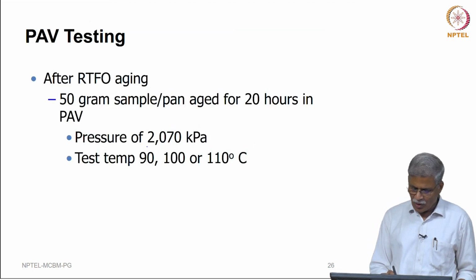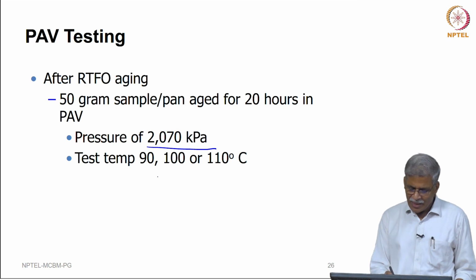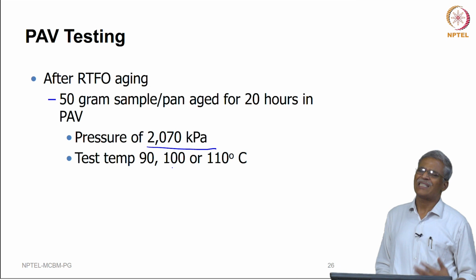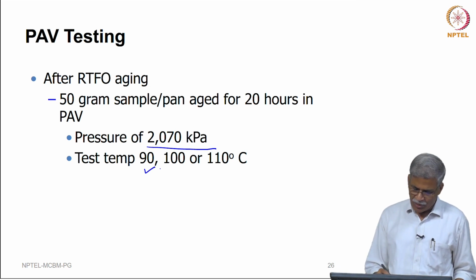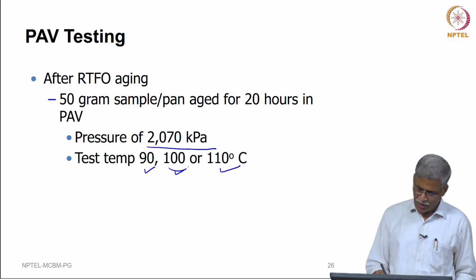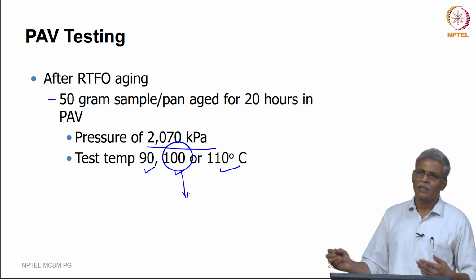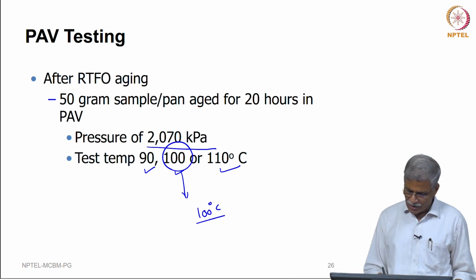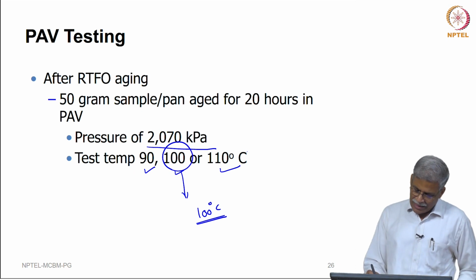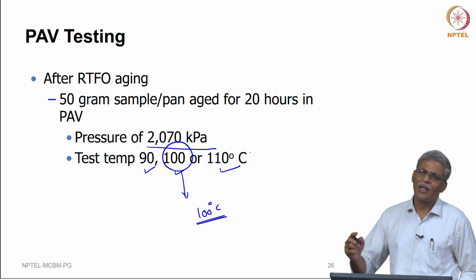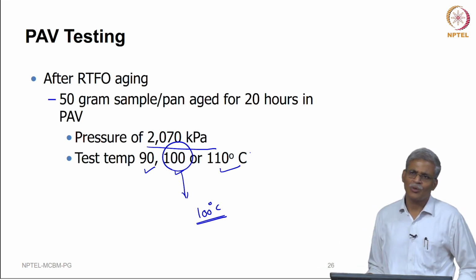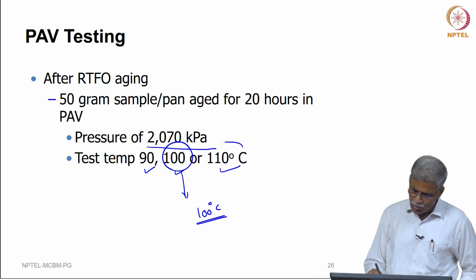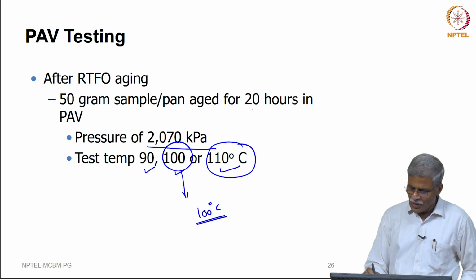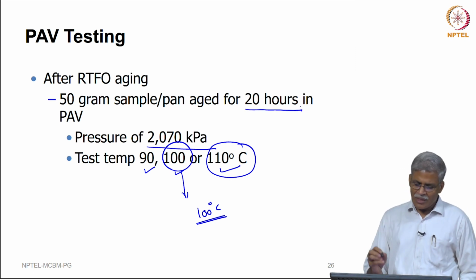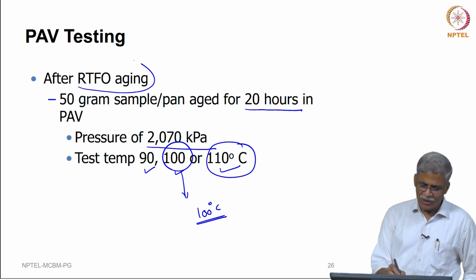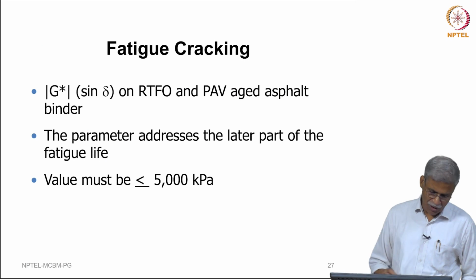So, what is the pressure? We are talking about 2070 kilopascal, and depending on the geographical location in which you are going to construct your pavement, one should pick a test temperature of 90, 100 or 110 degree centigrade. For conditions that exist at Chennai, we normally do it at 100 degree centigrade. In locations such as Rajasthan, where the summer temperature is high as well as the winter temperature is low, one should be able to do it at 110 degree centigrade. So, this aging goes for 20 hours, and this is the material that should be aged after the binder is subjected to short term aging in RTFO, right.